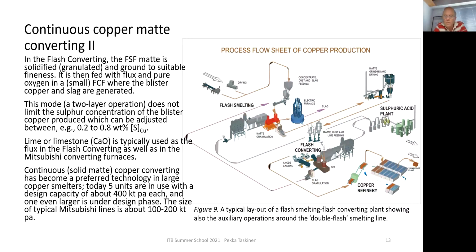And these flash converting furnaces are then much smaller than flash smelting furnaces, and they don't have three layers. They don't have a matte layer in between slag and blister copper. They are operating in two-layer mode, and that is why the sulfur content of the forming blister copper can be anything. It can be saturated with matte, which is more than 1%, but it can be oxidized down to 0.2 weight percent. So then we don't need any specific fine refining technology for treating that material anymore.